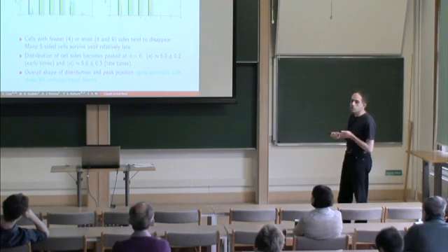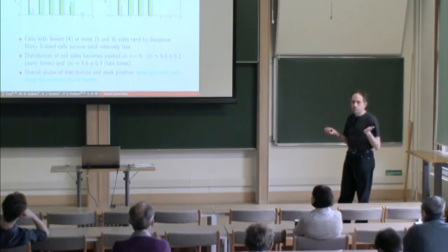And what we see is that the foam is being enriched in 6s, 5s, and 7s. And again, this is qualitatively what you get in a liquid foam. The exact shape of this distribution depends slightly on the method of preparation of your foam, but in pretty much all foams what you have is mostly 6s and also lots of 5s, as you see there, and of course if you have 5s you've got to have 7s for topological reasons.